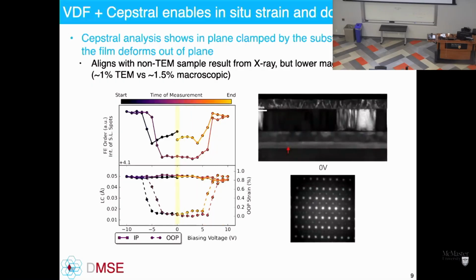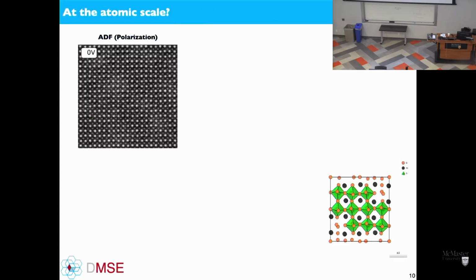So all that I've shown you so far is what's going on macroscopically, relatively macroscopically, right? I mean, it's at the micron scale, but we don't see what's going on at the atomic scale in terms of what phases are present and where. But with modern in situ and operando type experiments in the electron microscope, we can actually apply a bias and watch the crystal structure respond at the atomic scale and create movies, essentially, of the atoms in action.